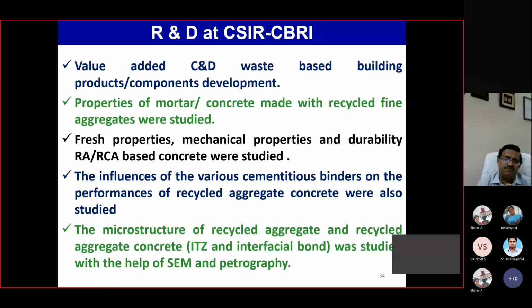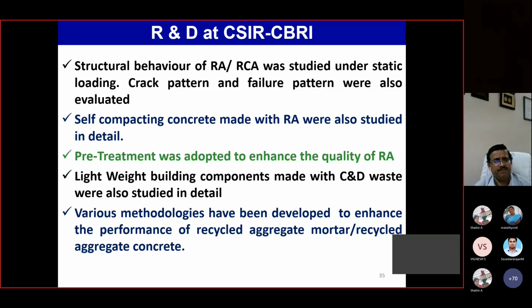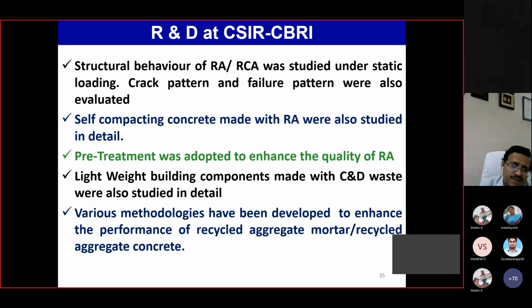Not only have we characterized different types of C&D waste, we have also worked out how we can improve their properties by mechanical means, and by chemical means at the interfacial zone, to achieve good strength. We have also tried different mixing processes, increasing the mixing time and adding cement or finer parts. I am not going much into those details, but definitely those things are there. The utilization of recycled coarse aggregate and fine aggregate is an utmost important thing.